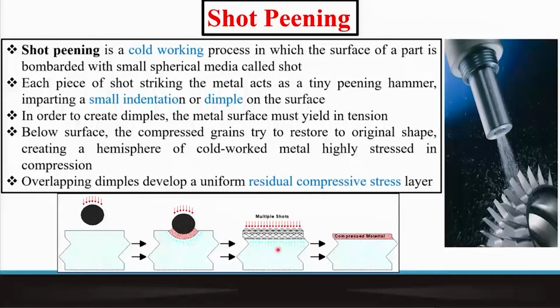This is for a single shot. If this happens multiple times, with a number of shots or spherical objects hitting the surface in tandem, covering the entire surface area, then you create an entire surface region up to a certain depth of residual compressive stress. So that's what shot peening is all about.